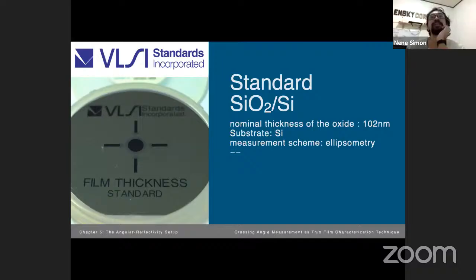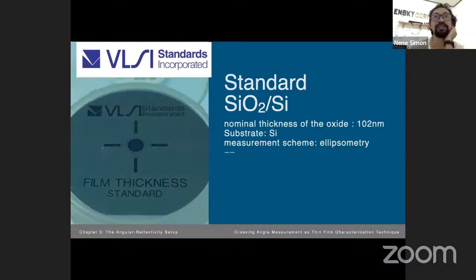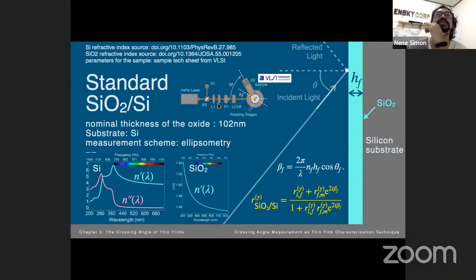The sample we used for this experiment is a standard sample, a silicon dioxide on silicon substrate, which we purchased from VLSI Standards. This sample has an oxide film thickness of 102 nanometers, which is measured by the company using ellipsometry. The substrate is silicon. From here we have this schematic diagram for our sample, and we will be using our reflectivity setup to measure its crossing angle. As shown earlier, the reflection coefficient is given by this equation, and we will be using the discussed dispersion related curves to predict the position of the crossing angle.